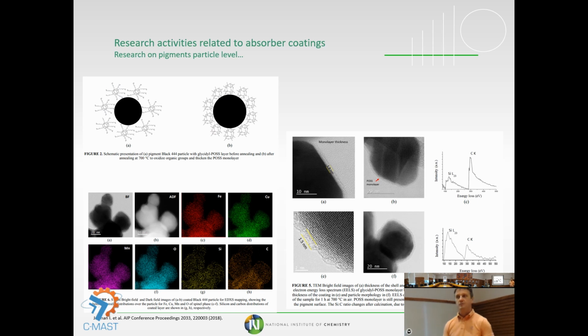I was working quite a lot on polyhedral oligomeric silsesquioxanes during my PhD. So we try to put them on the surface. You could tune the pendant group on the smallest known silica. It is an octahedral system, eight silicon atoms in the corners connected over oxygen bridges, and on those corners you could apply different pendant groups. Some groups are responsible for connection with the substrate, in this case a pigment particle. It is also important that pigments are well dispersed inside the paint in order to produce a uniform layer and gain high solar absorptivity.